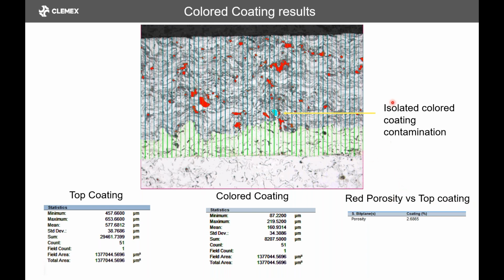the whole thing. I would like to point out here that we can also pick up some contaminants. Like in this case, it was a contamination from the bond coat that was chipped, but it's not really part of the coating. So I want to point out that we can isolate contamination in the coatings.